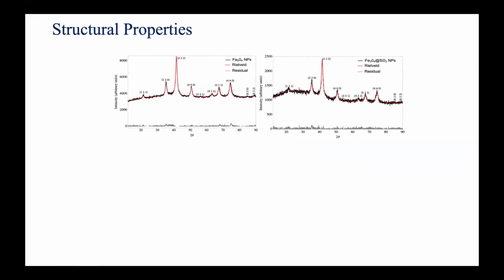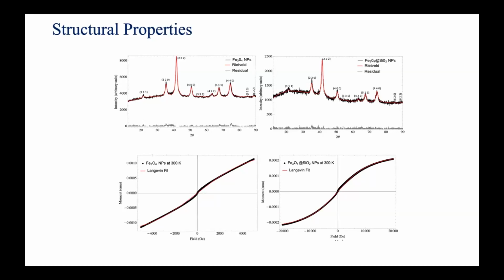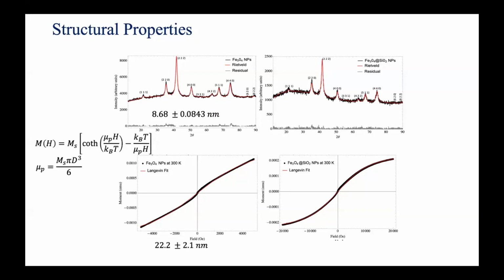One of the problems with magnetite is that it is highly magnetic, so we couldn't get a chance to look at it under a microscope. To work around this and determine the size, we use two methods: the Langevin equations and Rietveld refinement to estimate the size of these nanoparticles. When you use Rietveld, you get about 8.6 nanometers, and when you use Langevin, you get about 22. But for the coated ones, the sizes increase from 8 to 12, and here we get about 35, which shows that there's a shell.